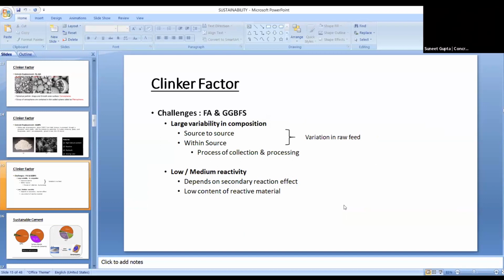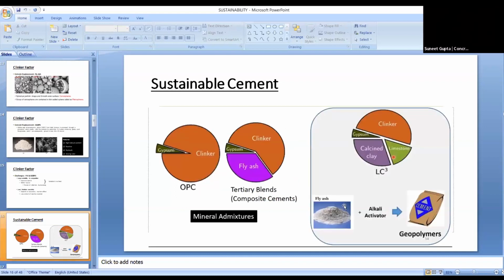So that's how the variability comes. And the second is the reactivity. The reactivity factor, as I told you in the previous slide, the reactive silica that we have is the most important factor in making the cement, and hence the concrete, more sustainable, more durable. So this kind of variability is due to the variability of the raw material which is consumed in making these. Further to the blended cement, Portland pozzolana cement, where we use fly ash, and Portland slag cement, where you use slag up to 50, 60% in cement.